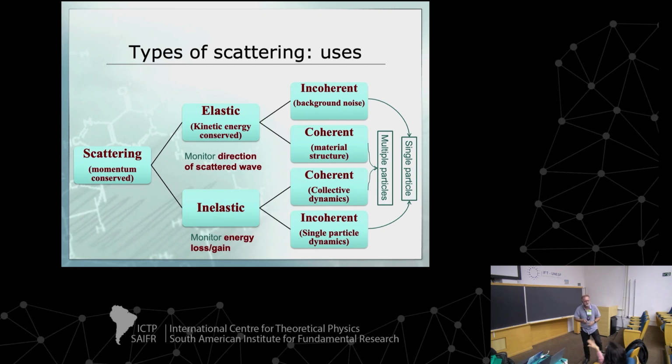And you cannot subtract. You do the experiment with mixing water and then subtract from an experiment with only water. It doesn't work like that. It affects the whole signal, and you get all these incoherent things, and the incoherent section is huge. So actually, it's really hard, and you have to work with deuterated water, which fortunately is relatively cheap.